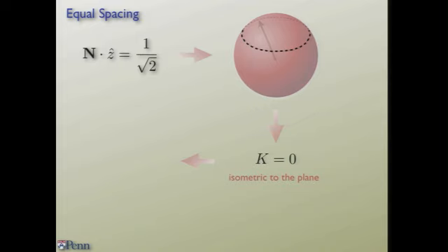The cool thing is if I want to have a surface, a two-dimensional smectic, it means that its green surface, which isn't the smectic, it's just that green surface, has to have its normal always pointing at 45 degrees. So its normal always lives on this curve, right? Well, you know what's cool about that? The area swept out by this normal is precisely the Gaussian curvature of the green surface. That's, you know, the whole point of the Gauss map.